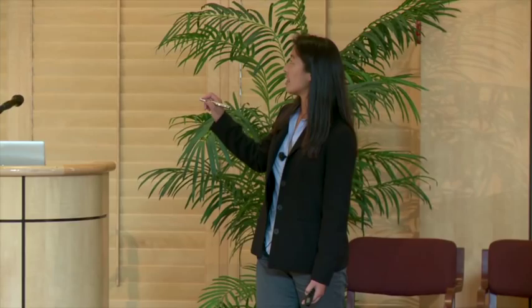So there are some key challenges in CO2 reduction and some key metrics that I'll be referring to throughout my talk, so I just want to introduce those metrics to you now. The first is, again, these two reactions at the cathode and at the anode that I mentioned, and this determines the amount of energy that we can store in the form of fuel. Unfortunately, we can only store that much energy if we have perfect catalysts that can operate at the thermodynamic minimum. Generally speaking, we need to apply a certain amount of overpotential. And so overpotential is a really crucial metric, and we want to keep that overpotential as low as possible so that we have the highest energetic efficiency.